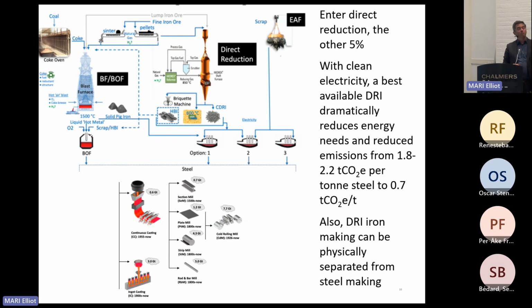Just going from the best available blast furnaces to DRI units, you cut emissions in half right there, boom. Also, if you construct your unit properly, the carbon monoxide that comes out of the top of the reactor is relatively concentrated, and you can do CCS on this if you're careful about it. There is a 60% capture plant in Abu Dhabi doing this today, and the CO2 goes to enhanced oil recovery.